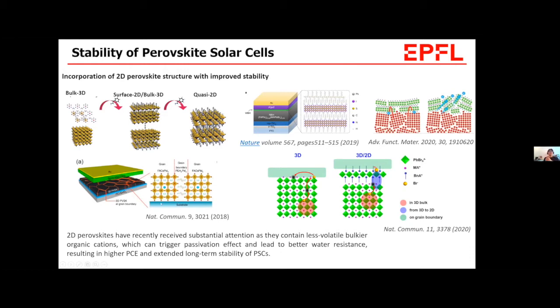In this case, you could mix the precursor solution with the 3D perovskite solution. If you put too much of the precursor to make 2D perovskite, the efficiency, and even the stability, will be very bad. So control of the amount of 2D perovskite precursor would be key. Or you could just make a low dimensional perovskite rather than 3D, 2D type. Then you're going to lose some efficiency, but you're going to gain some stability, because 2D perovskite is more stable than 3D perovskite.